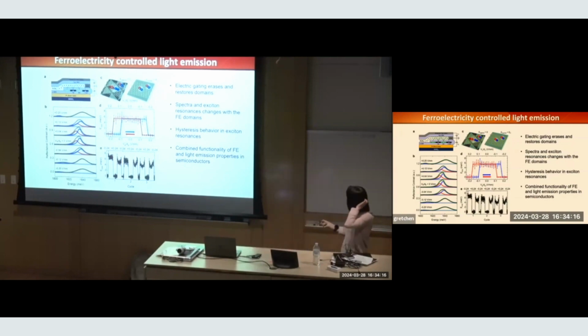So in this case, I want to convince you that I was actually able to combine the functionality of ferroelectricity from the hBN substrate with the light emitting property in the semiconductor. I have an electrically switchable light emitting material in this heterostructure because I have ferroelectricity just by folding the hBN and the light emitting property from the functional layer. I really feel that it's a great platform. Use your imagination for what you can put on the surface.